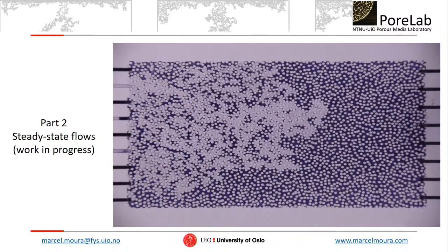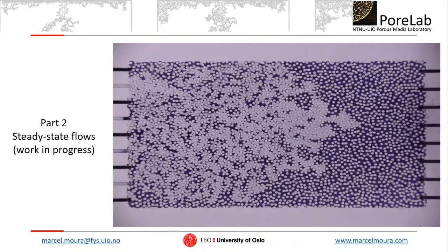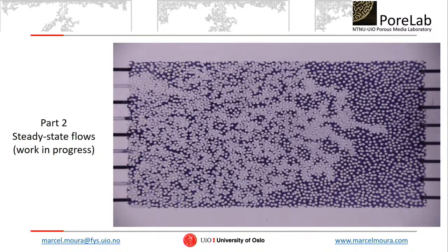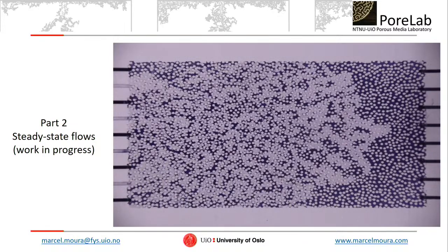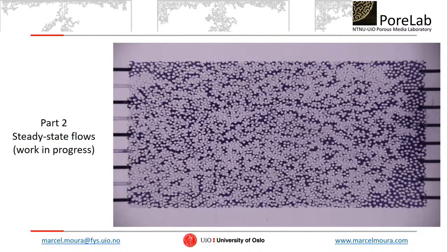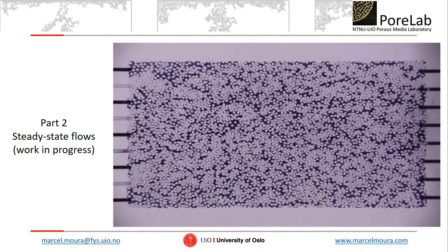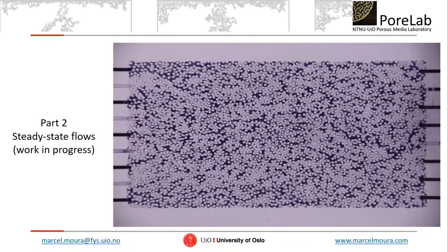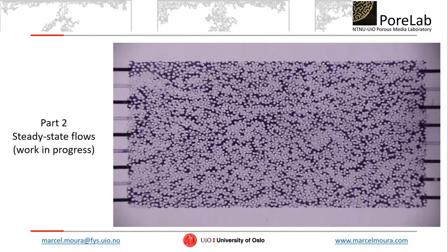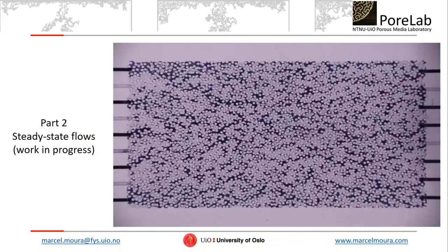Yeah. So here, the blue one is more, I mean, the system is more water wet than oil wet. The water is the blue one, but it's not as great a contrast as in the case of the glass beads, because the glass beads are really very water wet. If we were to measure the contact angle of a little drop, it's very small, like 15 degrees, 20 degrees. In this case, it's more around 60, 70 degrees. So it is slightly water wet.